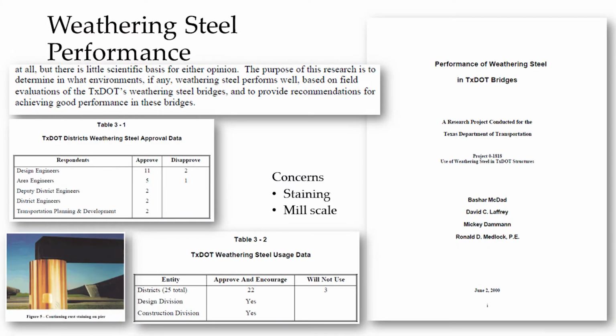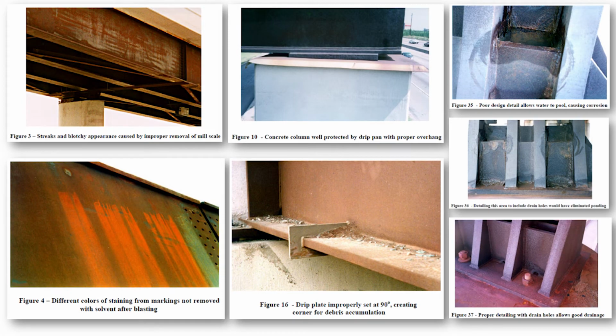One of the concerns is mill scale, and that was, if you looked at the district responses, one of them was, we don't like it because of mill scale. And certainly it is rather unsightly. This top left picture, if you don't take the mill scale off, it could be there 20, 30 years. So it's not going anywhere. There was a requirement in the TxDOT specs that the mill scale be removed, but what we found out in doing the study, contractors would say, hey, we'll do that in the field instead of the shop, and that would get okayed.